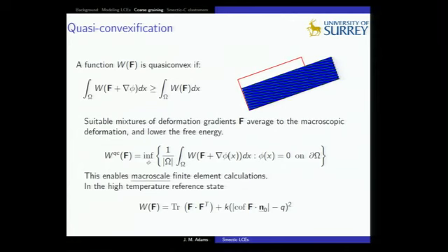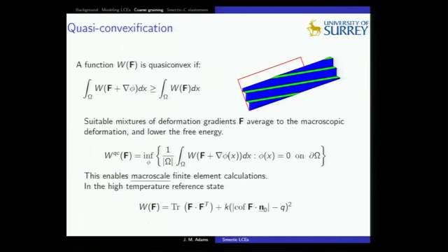So the first thing to do is, instead of working in the low temperature Smectic A phase, where you have this sort of energy with these L tensors and it's more difficult to see what's going on, to transform to the high temperature isotropic phase by using a composition that includes the spontaneous deformation, in which case you find that the free energy is given by this expression, provided that the determinant of F is 1.